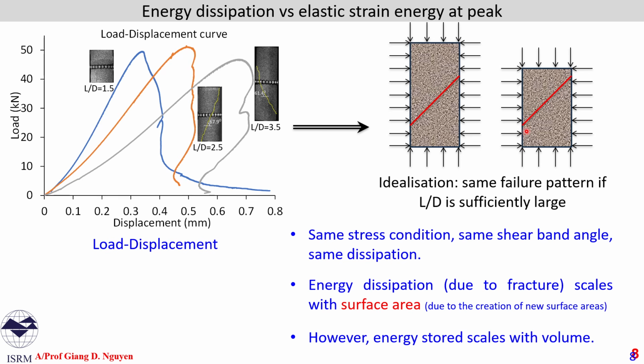So the conclusion here is, if they are under the same stress conditions, they should have the same shear band angle and the same dissipation, that means dissipation due to the creation and evolution of the shear band. If the dissipation is due to fracture, it scales with the surface area due to the creation of new surface areas. But if we look at the whole specimen under the same stress condition, at the peak they store different amounts of energy. The peaks of all three specimens are roughly the same, and theoretically they should be the same because they are of the same material, and failure happens at peak under the same stress threshold.